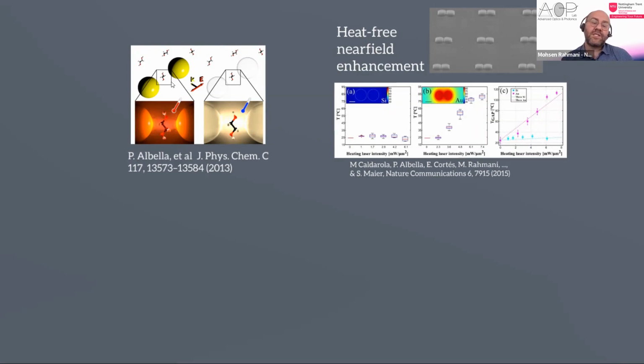Here, actually, it was a nice paper. It's my friend Pablo Albella. Many years ago, he showed this effect very nicely theoretically, that as compared to the plasmonic nanostructures, which generate heat together with the hotspots, the dielectric nanostructures and dielectric hotspot are heatless and heat-free. And as you see here in this experimental result, we already showed it in 2015, that it is indeed the case. And silicon dimers do not generate heat, but plasmonic dimers, gold dimers, can generate up to 80 degrees.